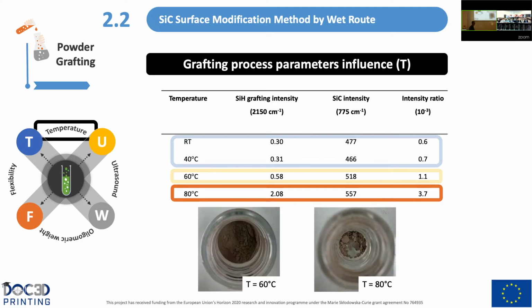Because after the surface modification process, at 60 degrees we have the silicon carbide in powder form, but at 80 degrees, instead of powder form, we are forming some silicon carbide plates because the temperature is leading to some cross-linking. And since we don't have the ceramic in powder form, we are not able to use it in the powder bed selective process.